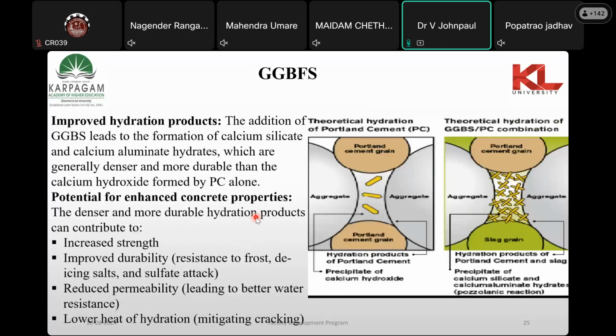If you just look into the picture, the left one shows the Portland cement. Interaction between these two aggregates is very less. There will be chance of porosity, thereby there will be reduction in durability because the resistance to sulfate attack and chloride attack will be very less. But if you look at the alternative, the GGBS, the interaction between the aggregate and the cement paste is very high in the hydration process due to the precipitation of calcium silicate or calcium aluminate. This happens to be the pozzolanic reaction, CSH gel formation. I'll show images in the further slides.